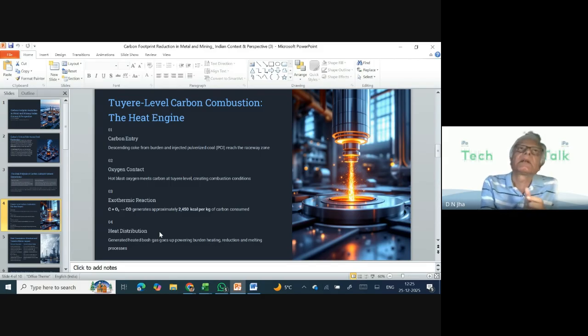So it is important that this heat transfer is a phenomenon which happens. Let's remember that the role of the carbon in the blast furnace itself, in whatever manner, is to provide heat. That is very important, because we have to melt the metallics, as well as we have to melt the slag. So this is the bare minimum. Apart from that, the heat is required to heat up the burden column itself gradually. So there is a heat requirement, and this heat is transferred to the burden, starting from the melting of the metal and going on to the top, where it simply evaporates the moisture. Okay, so this is a very, very important phenomenon which happens.